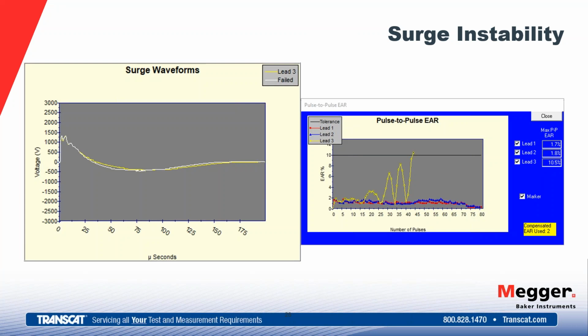So here we get an example of a surge waveform on the left. Yellow is the good waveform. The very next pulse actually caused the inductance of that system to go down, shifting the waveform to the left. So the white one is that failed waveform. And we're going to quantify how much it shifted here in our pulse-to-pulse EAR. As we see this activity here, that's an indication that we've got a weak turn-to-turn insulation.